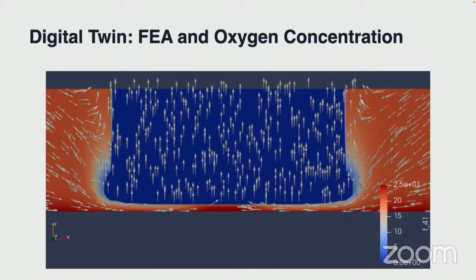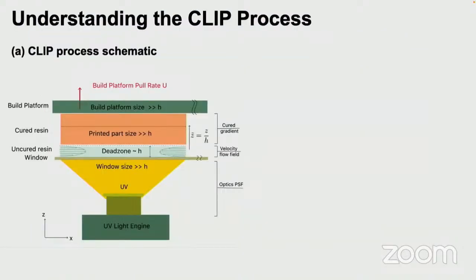There's a lot happening. There's heat evolution, there's oxygen consumption, viscosity issues play a really key role. There's a lot of forces on the part, so the green strength of the part as you're pulling on it matters, and this is just a simple geometry. I'm showing you just a cylinder, but imagine if you're making a complex lattice and the part is elastic. You can deform it and screw it up. So this is a complicated process. I think of this as a software-controlled chemical reaction to grow the parts, because we have to bring a lot of understanding to the process to even get it to work.